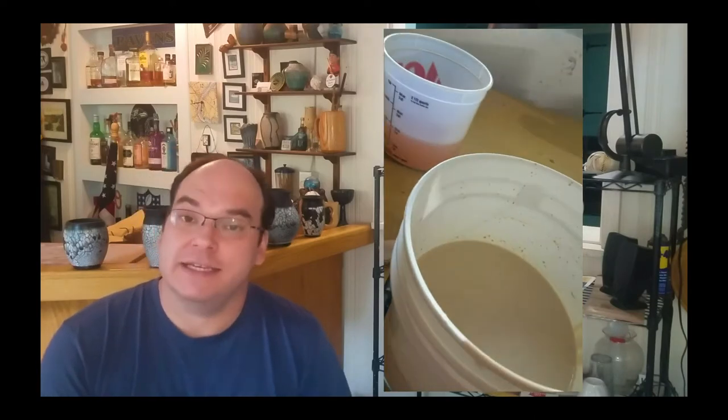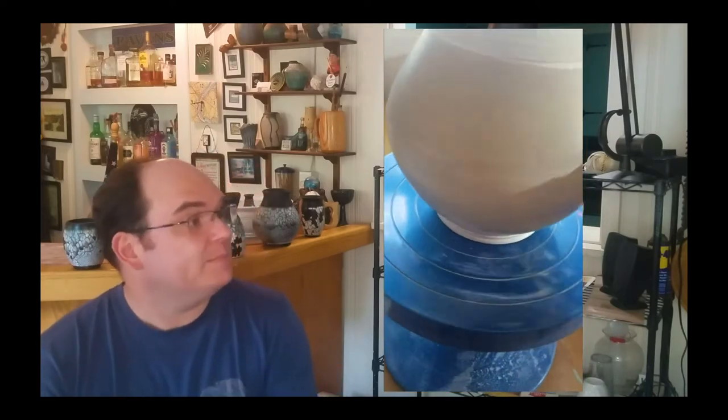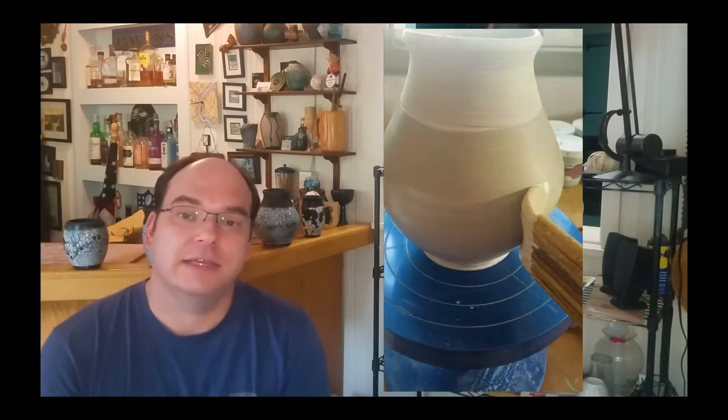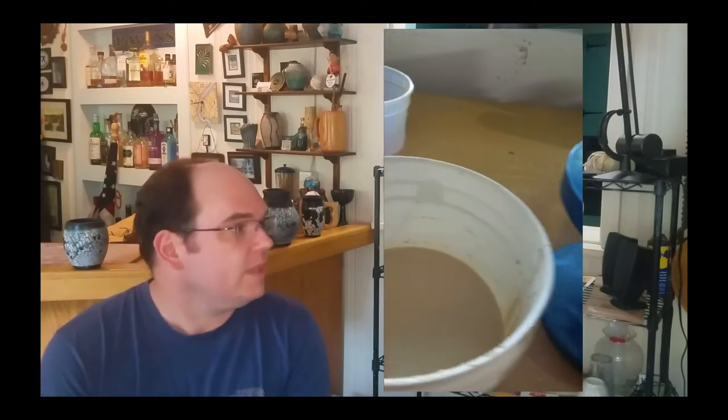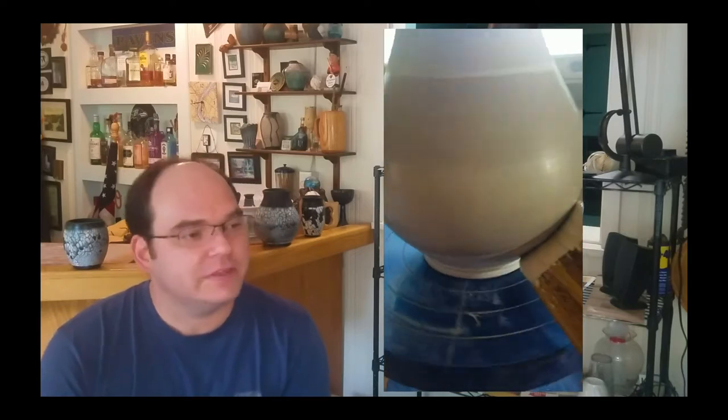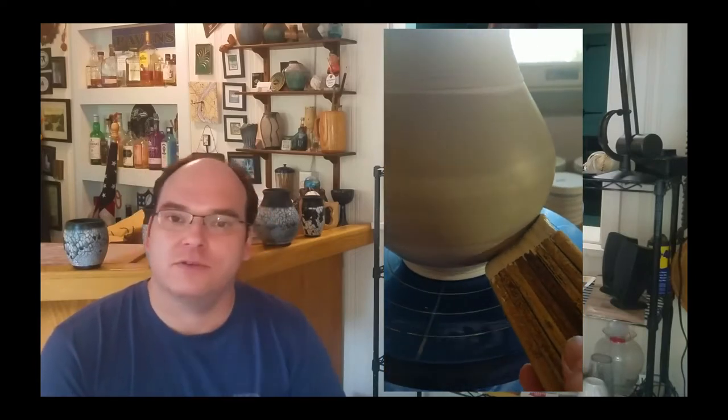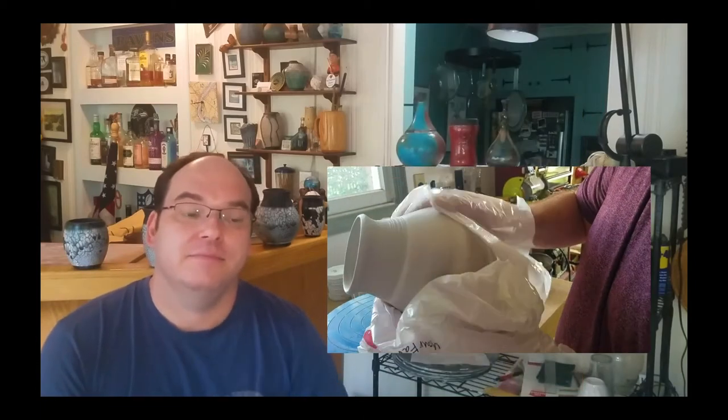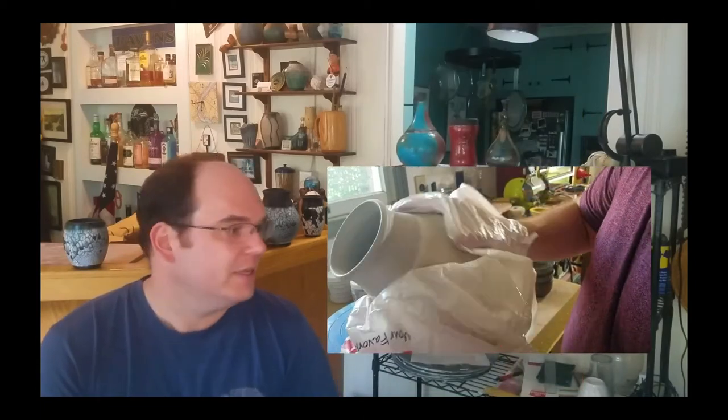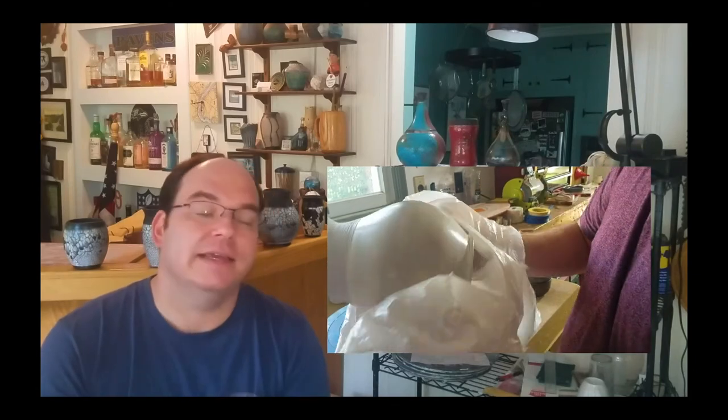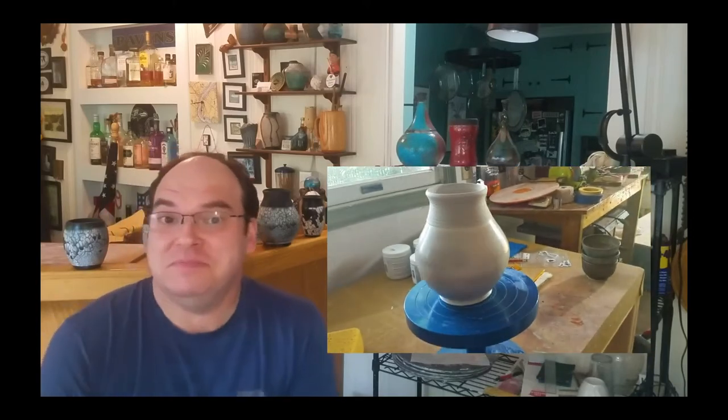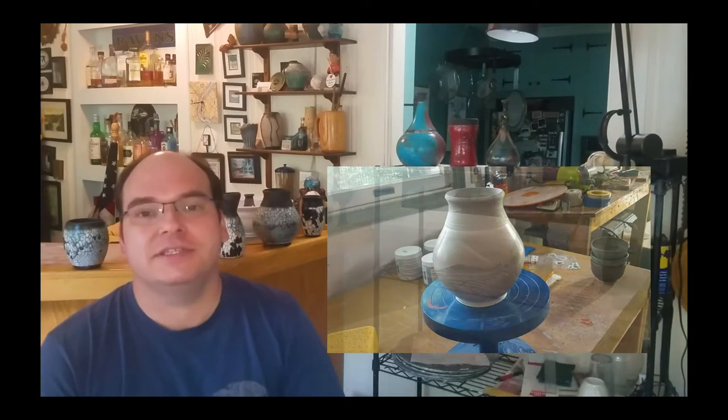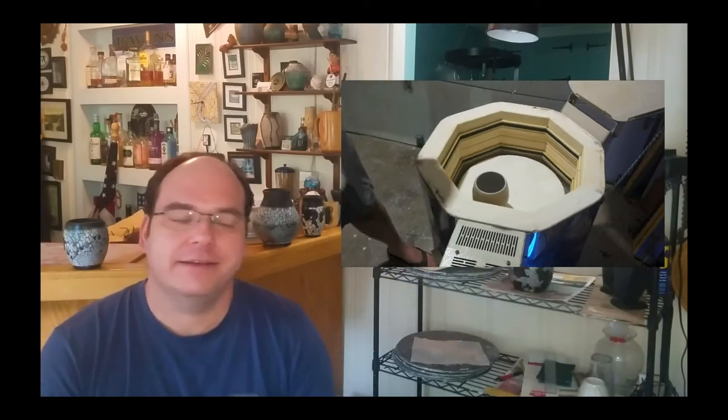After you've burnished your leather hard piece, you let it dry to full bone dry. Then comes the next step and the next step is applying terra sigillata to the outside of the piece. And what the terra sigillata will do is fill in a lot of the gaps, fill in a little cracks, smooth out the surface and make a highly polishable surface. As you can see here we are taking plastic bags, you can use gloves, you can use a lint-free cloth. The plastic bags really actually end up being really nice and you polish the terra sigillata to a high shine.